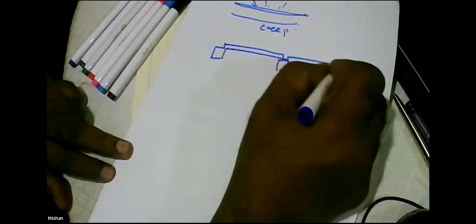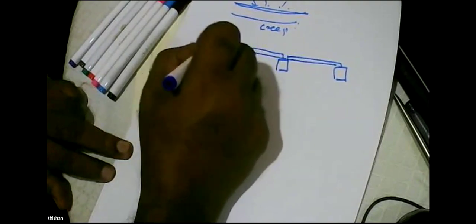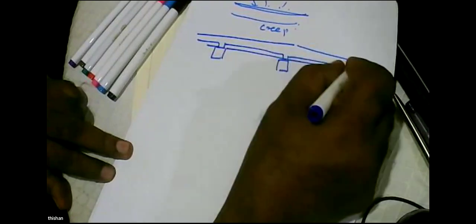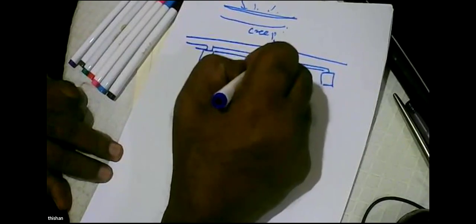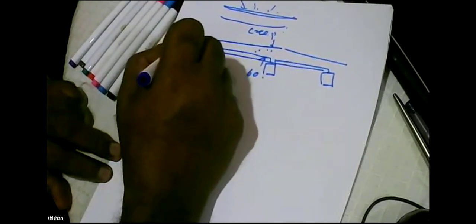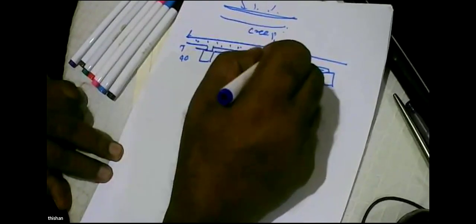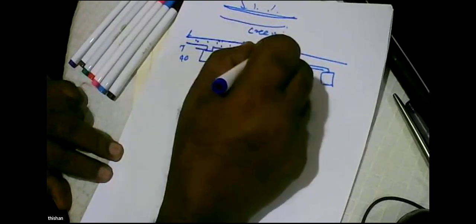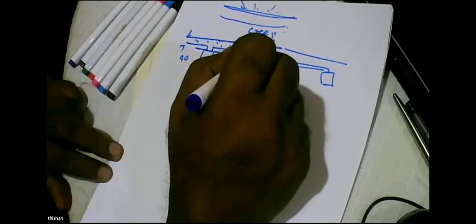why do rooftops leak? We do solid slabs, they sag. And then water stagnates. And with time, due to creep deformations, these sag, and we have problems. But here, we have a slab which does not deflect, lightweight, and very deep, so this can be altogether 300 millimeters deep. What you can do is lay the screed to a slope. Maybe the screed here may be 60, the screed here may be 40. So you lay it to a slope and you use all these marble type materials and make the top surface rough. The moment you do this, you will find waterproofing is not essential.